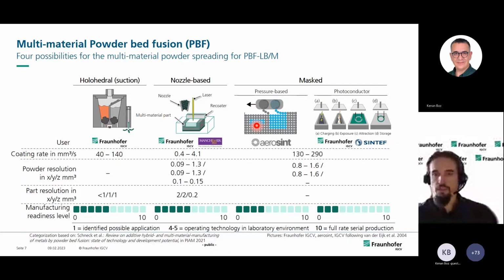So here we can, for example, see the pressure-based mask systems as developed by Aerosint. Here you've got two drums which have a lower pressure on the inside, so powder is sticking onto the drums, and then a nozzle selectively removes the powder along the contour. And this is done with two drums, one for material A, one for material B.